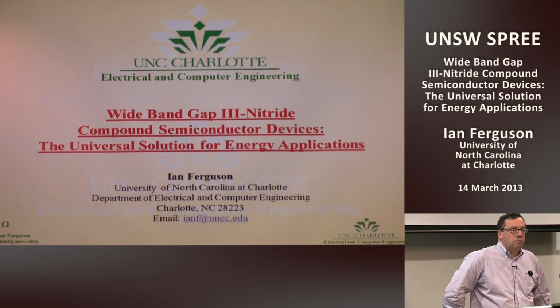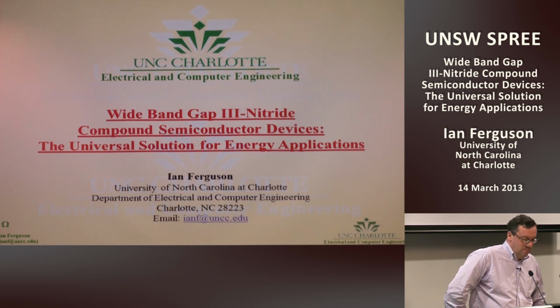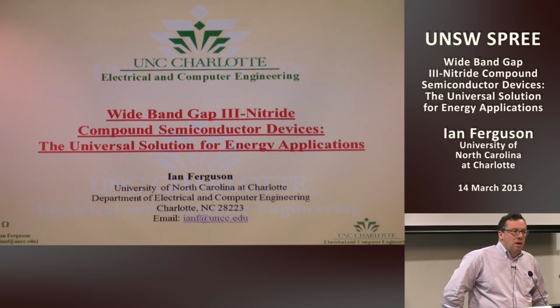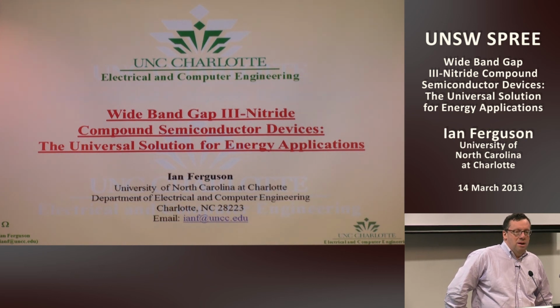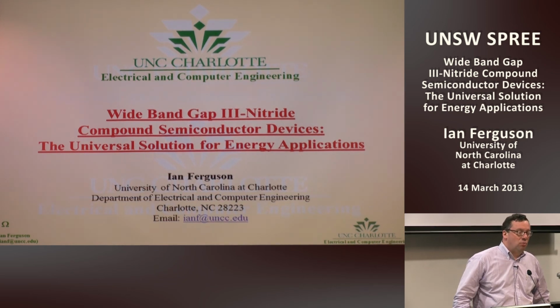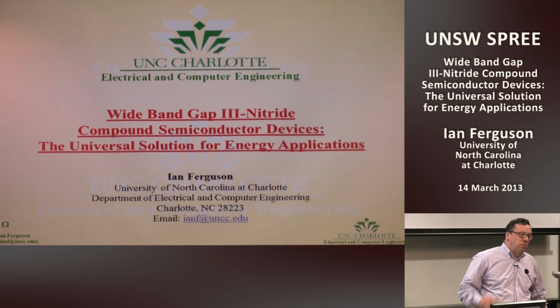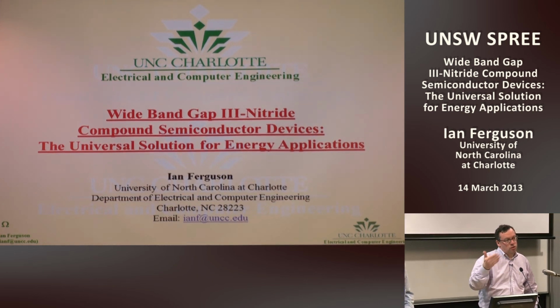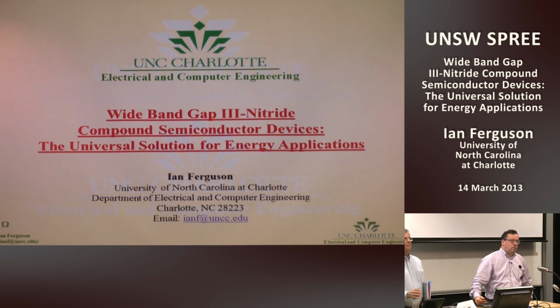And with MOCVD grown films, there's sometimes an issue with carbon and hydrogen contamination? Not really. Hydrogen anneals out of most semiconductor materials really, really quickly. Carbon really depends on the sources you use and the growth temperature.